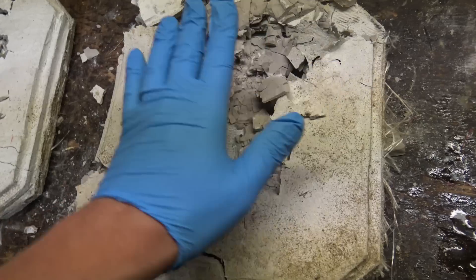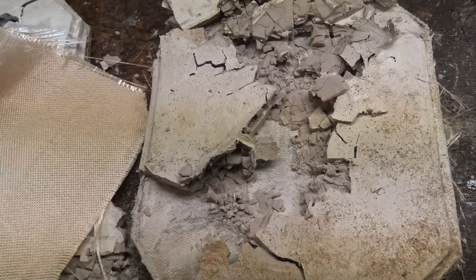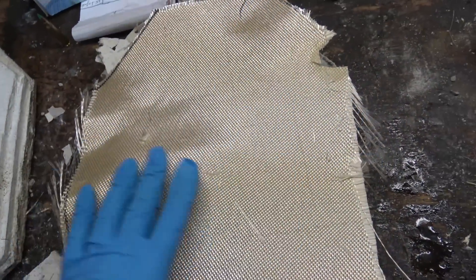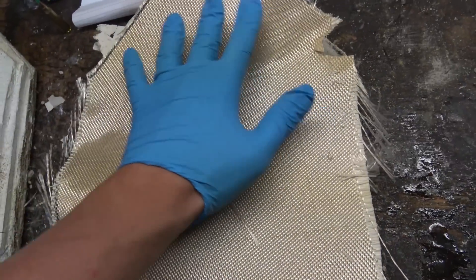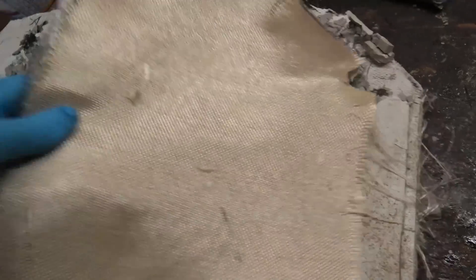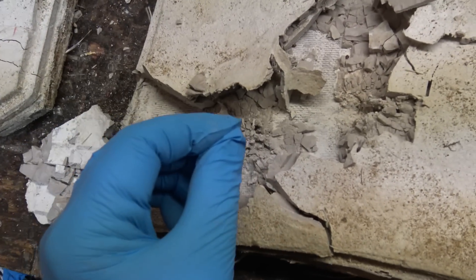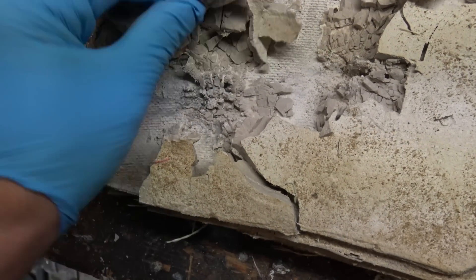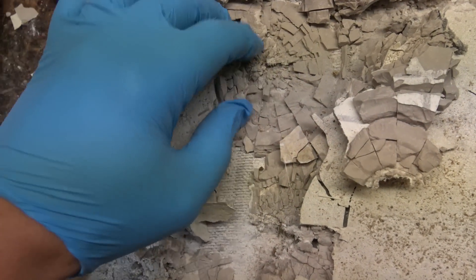After shooting, some of these held together really well. One Mosin shot at the bottom kind of broke and shot a piece off. One way to mitigate that is to add an extra layer of fiberglass on top when using this polymer coating — I think it would act as a way to keep the ceramic together better from blowing off with bigger bullets. The smaller high-velocity bullets will just keep barreling through, but the big ones just disintegrate on the ceramic and throw ceramic all over the place.